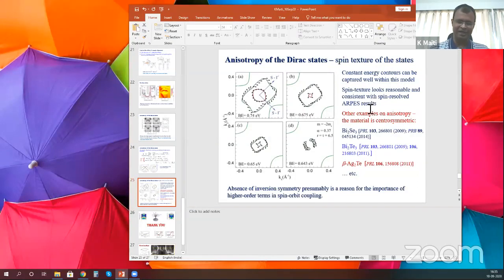Okay, sorry, Priya. I think I was thinking something differently. You are right. The DFT result shows the anisotropic Dirac states. That's correct. But why we went to K.P is really to understand what exactly is happening: what is the role of spin orbit coupling, what is the role of inversion symmetry and so on. In DFT, of course, you do get the energy bands, which show some kind of anisotropy in the Dirac nodes. We have seen in the calculation itself that if you look at, say, S gamma direction and S gamma prime direction, they are different. That means the spin splitting of the bands is different, so there is an anisotropy. We went to K.P just to understand what is the physics behind.